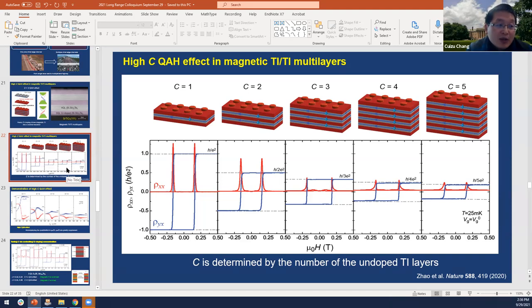So when I was talking with my theoretical collaborator, my colleague Professor Chaoxing Liu, he told me that if you grow this, let's take this kind of sandwich layer as an example, there are two C equals one quantum anomalous Hall layers. From the theoretical point of view, if you put anything between these C equals one quantum anomalous Hall layers, there should always be interaction, which should be exponential decay. It cannot become zero. That's from a theorist's point of view.